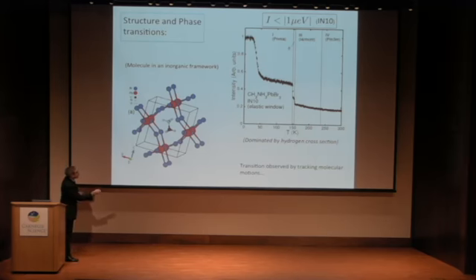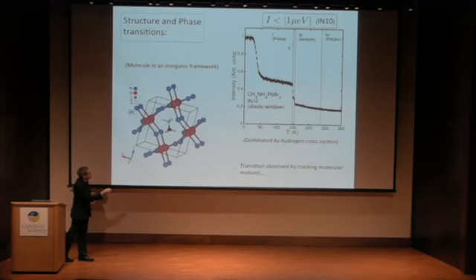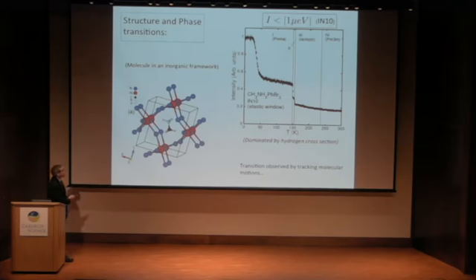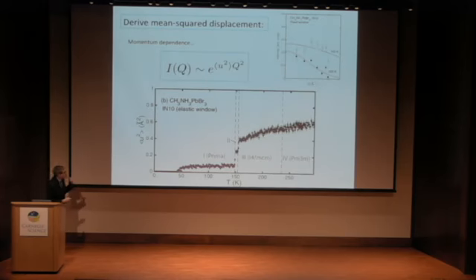Then at the various phase transitions, first of all, when you go over to the tetragonal unit cell, you see a drop, which is associated with something changing in the dynamics. Then you carry on up to high temperatures. You can see there is some action here in this intermediate, what's thought to be an incommensurate phase. Now, that's pretty qualitative, but we can assign some numbers based on the scan. If you plot out the momentum dependence of the scattering, you can extract a mean squared displacement associated with these hydrogen atoms. And that's what we've done here.